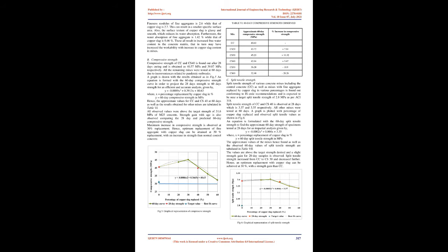Also, the surface texture of copper slag is glassy and smooth, which reduces its water absorption. Furthermore, the water absorption of fine aggregate is 1.42% while that of copper slag is 0.46%. These all result in increased free water content in the concrete matrix, that in turn may have increased the workability with increase in copper slag content in mixes.